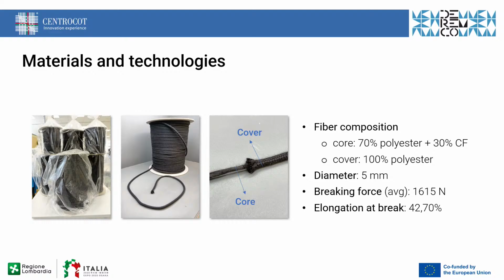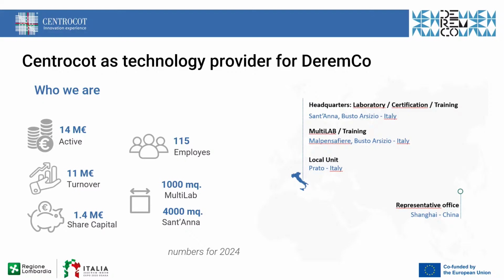but the interesting part is the mechanical properties of this rope. The breaking force is more than 1,600 newtons. That corresponds to more or less a load of about 160 kilos, so quite a lot. And the elongation at break is more than 43%, around 43%. This corresponds to a high strength and elastic rope that can be used for many applications, such as sports, protection, and construction, and many applications, because this rope can absorb a lot of energy before breaking, and also demonstrating quite good elasticity.